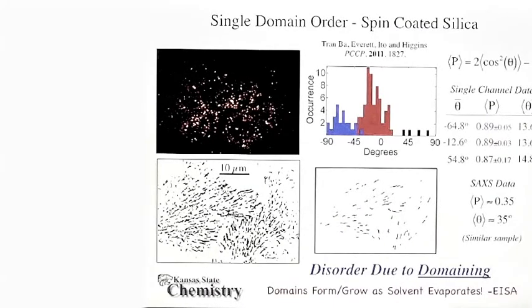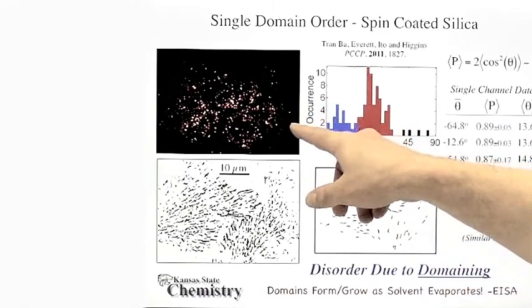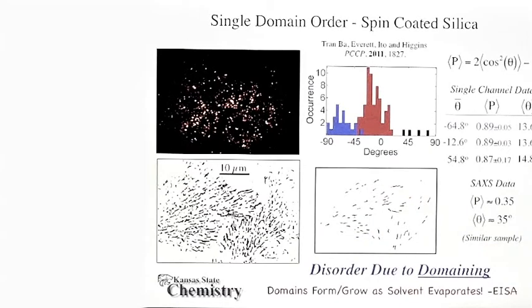We've used single molecule tracking methods as a means to explore the origins of disorder in spin-coated surfactant-templated mesoporous silica films. Shown here is a video and the associated trajectories derived from that video.